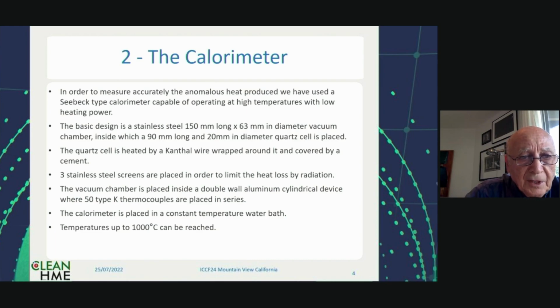The calorimeter. It's a Seebeck type calorimeter. That means we are using 50 thermocouples placed in series so that you can measure the heat flow that way. It's something very well known and very precise, but we have adapted the design so that we can go to high temperatures. The basic design is a stainless steel vacuum chamber, 150 millimeter long by 63 millimeter in diameter, inside which we can put quartz cells of different dimensions. Typically, I use 90 millimeter long and 20 millimeter in diameter, but we could use different types of cells if necessary.